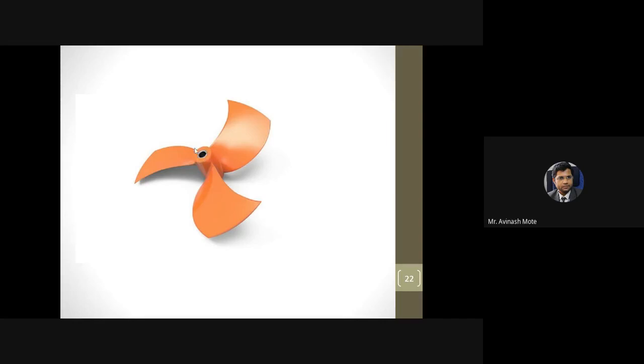But when the material is in a liquid state before pouring into the mold, if you use this insert, and the material collects around this component, now what is going to happen? This material is in a hot liquid state. While it is solidifying, it will solidify very close to the outside surface of this insert. It will hold it very tightly. This tightness is possible only if you go for molded-in inserts, whenever it is in a liquid state.